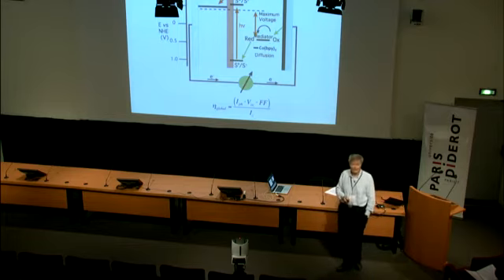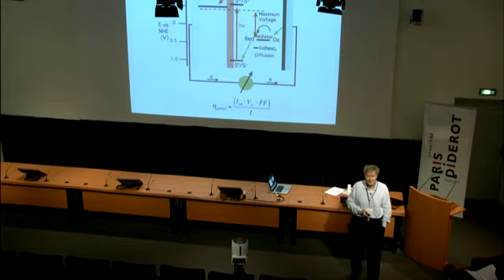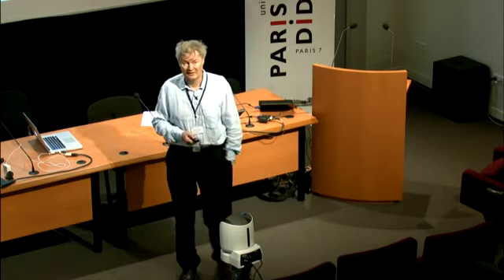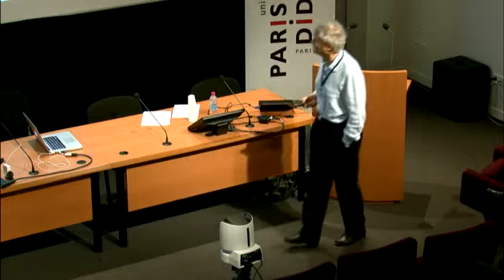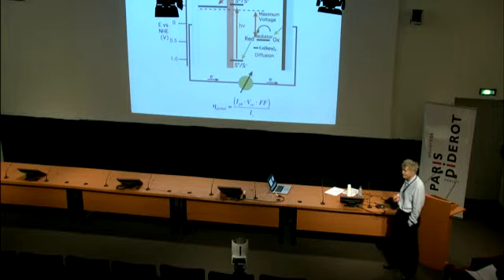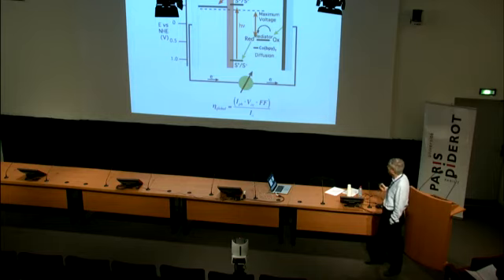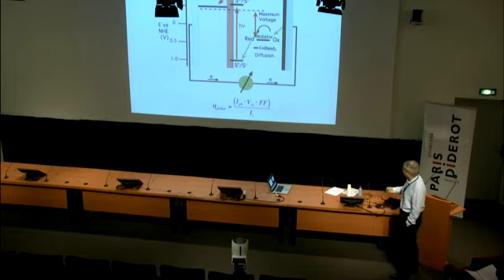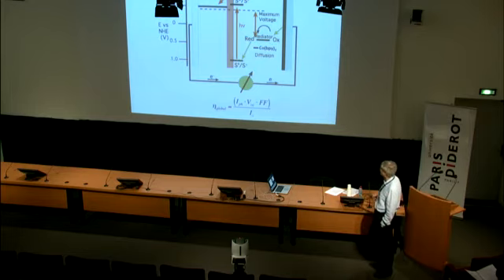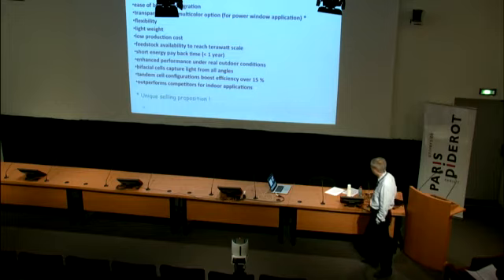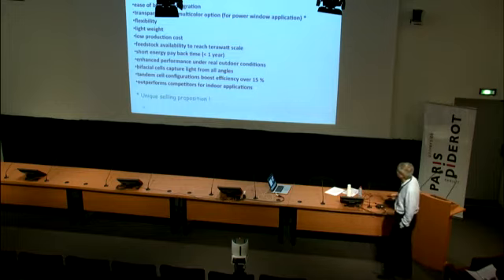And we have been able to get up to 1.1 volt VOC, which is one of the highest among photovoltaic cells. If I think about gallium arsenide, I'm not so sure, it may be close, but it's an amazingly high potential. It comes with a high current. So with this latest breakthrough, we have a good chance to hit the 15% bar for the DSC systems. Now let me move forward and show you some applications.